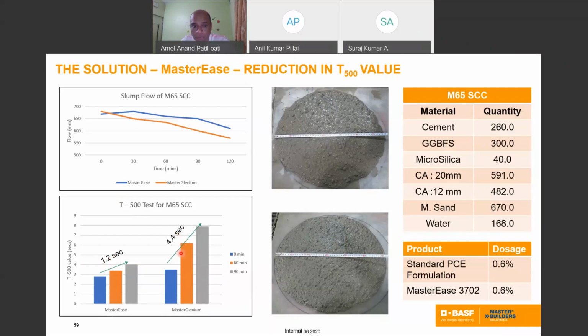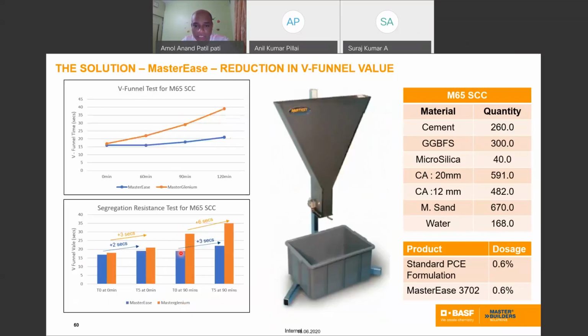In a similar way, if you observe the V funnel, the V funnel value for this Master admixture ranges from 15 seconds at 0 minute, and after 120 minutes hardly changes, to 20 seconds. But if you are using a different admixture technology, this is a low viscosity concrete concept. The viscosity changes from here with the other alternative at 0 minute, 60 minute, 90 minute, 120 minute. The behavior is different for each grade of concrete. The mixing, placing, transportation, all these practices are impacted differently.